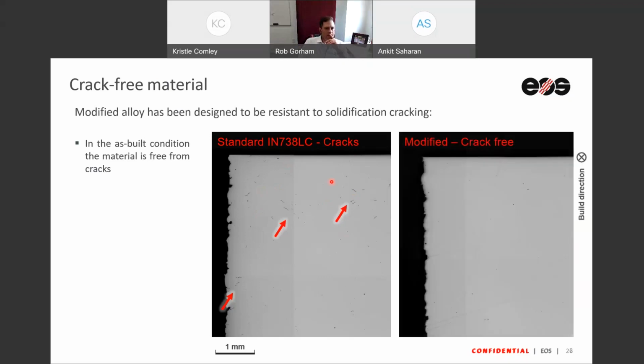And what we've done is we modified the 738 chemistry slightly. It drives the chemistry a little outside the bounds of traditional 738, but the resulting microstructure is crack-free. In that sense, what I want to say is that not every conventional alloy can be done additively, but you can have existing alloys modified that are meant for the additive process that are not only going to be defect-free, but can also drive performance much higher.